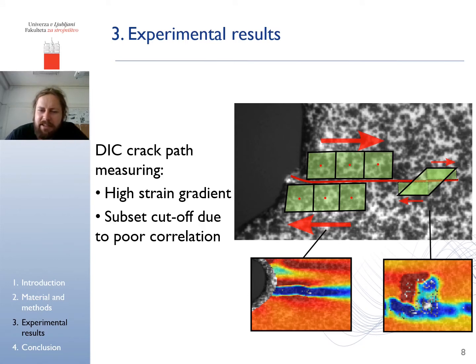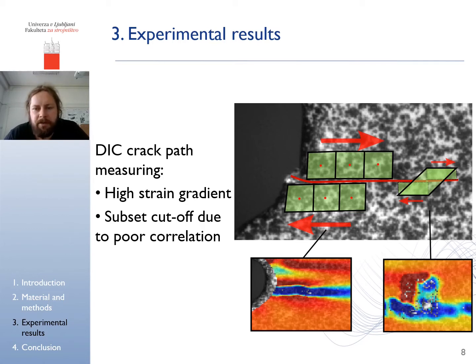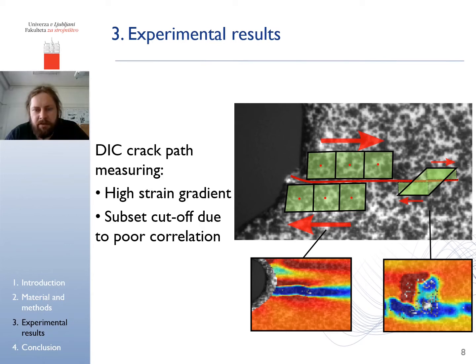As the crack progresses, DIC shows this crack as a means of high strain gradient. As we see on this first example, subsets above the crack move in that direction and subsets below the crack move in this direction — this is our shear direction. This is seen as a great gradient across this normally uniform field. Another way to view the crack is to look at this example where a crack grows through a subset. As the crack grows through the subset, it separates this subset and the Ncorr algorithm fails to correlate its position because it is being torn apart. This is seen as subset cut-off and it is seen on this real picture as the gray area with no real data.